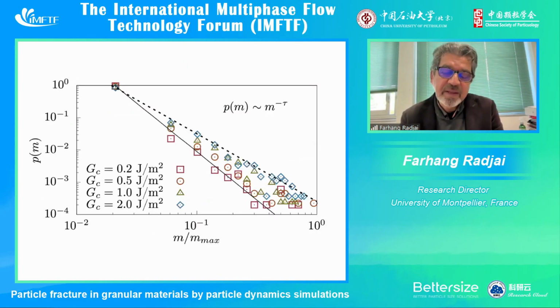And we also found the particle size distributions in the middle range of the values, because we don't have to consider very big fragments and very small fragments, where we have limits. These are the limits of the model because we can't go to very, very fine particles due to numerical efficiency. And we found, in general, that the particle masses have a power law distribution, as you can see here with a parameter tau, which has generally a value close to what we observe in many materials, something between 2 and 4.